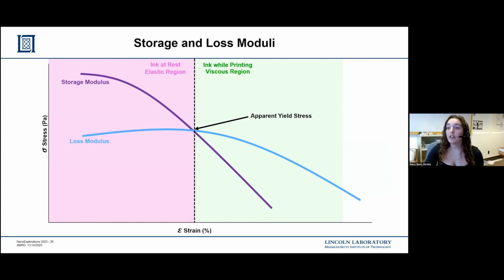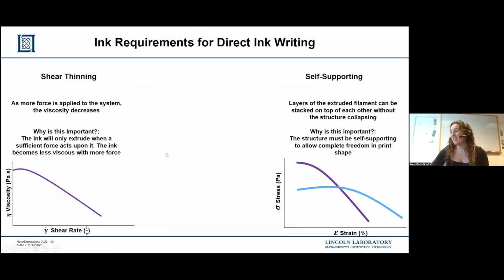So when you plot your storage modulus and your loss modulus on a stress strain curve, you get this intersection at the apparent yield stress. Before the intersection, it tells you about your elastic region. And after the intersection, it tells you about your viscous region. So it tells you that your ink will be able to flow cleanly out of the nozzle, but it will also be able to support itself once it's on the build plate. All right, going through, we know that our inks need to be shear thinning and self-supporting, right?